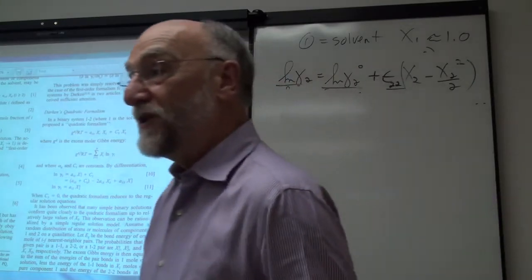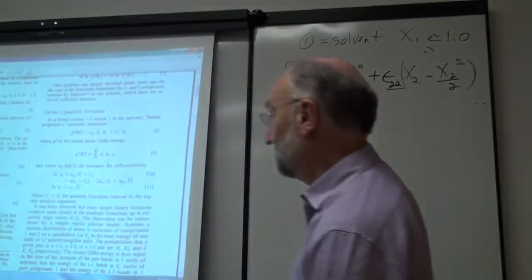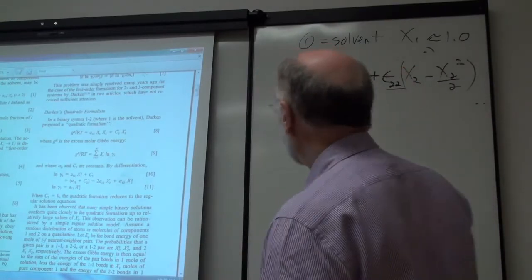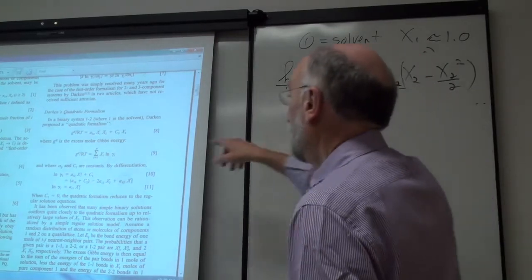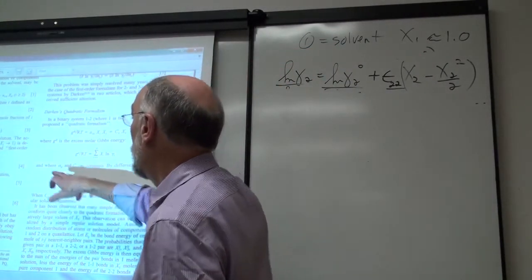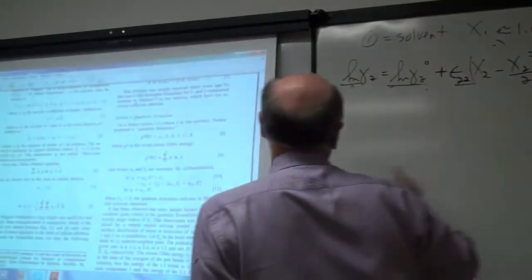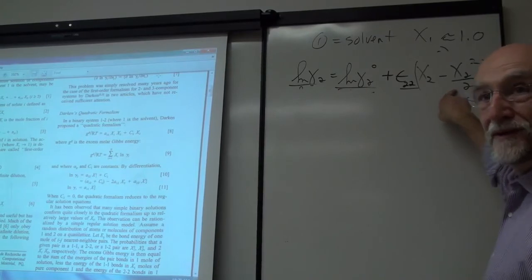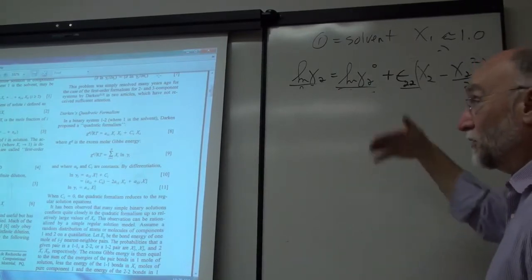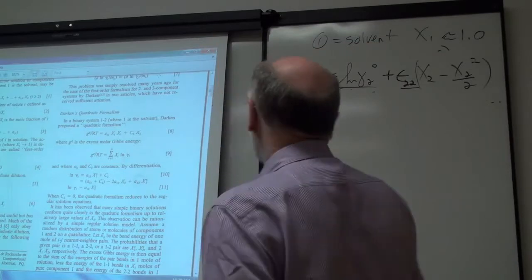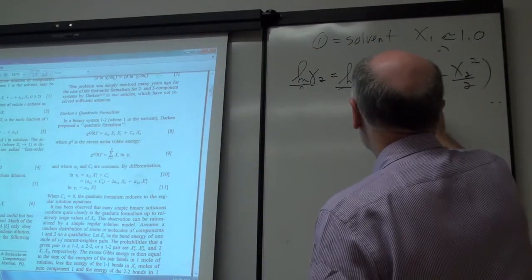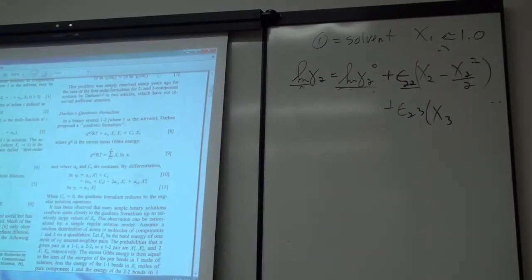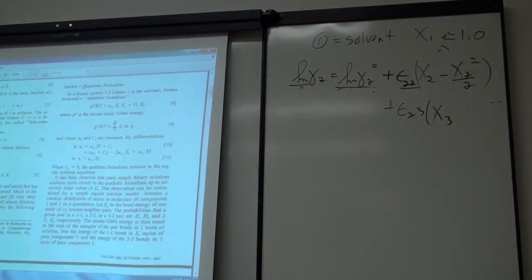Okay, so this then suggests very quickly a very simple fix for Wagner's equation. You don't have to rewrite anything differently. You simply say that in Wagner's equation you take exactly the same coefficients that Wagner used, the epsilons, but instead of saying x2, you say x2 minus x2 squared over 2. And then you got it. And when you go to ternary systems, we can show again the ternary term epsilon 2,3 should be x3, and I can't remember what it was now, but there should be a term that you add on to that. I cannot remember it.